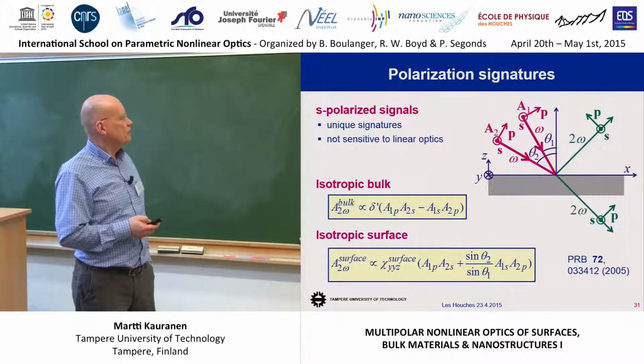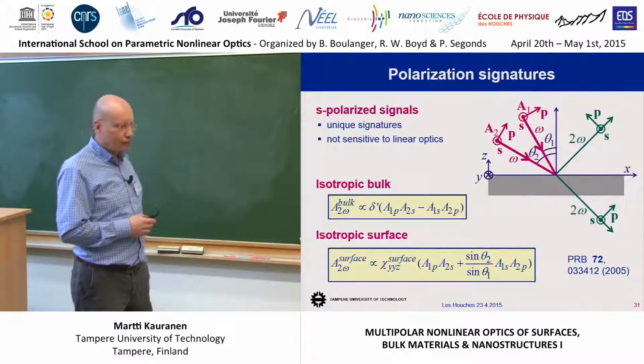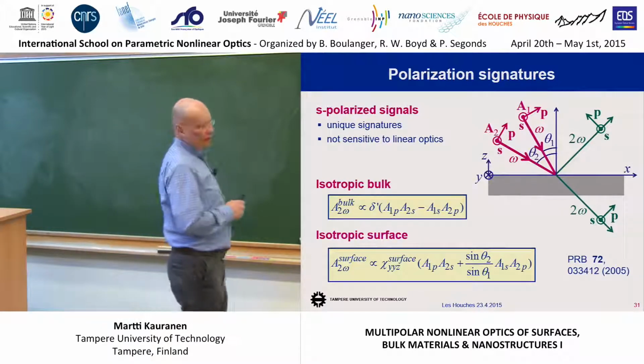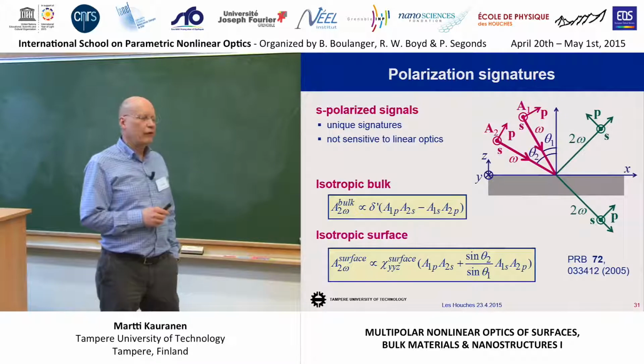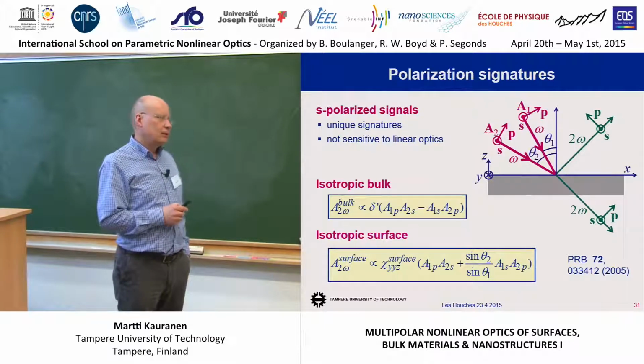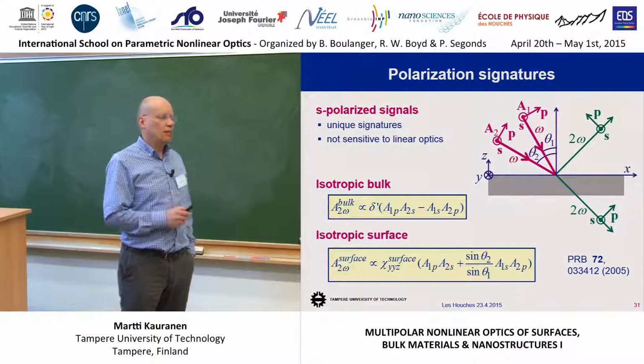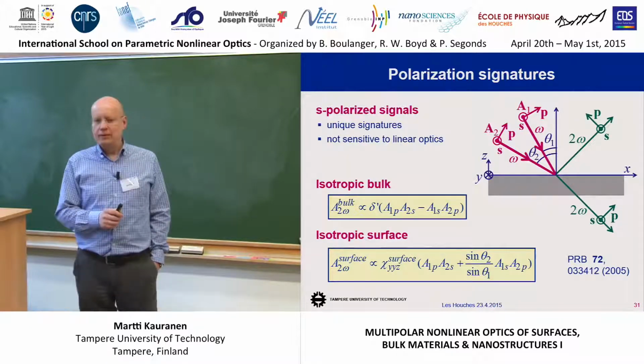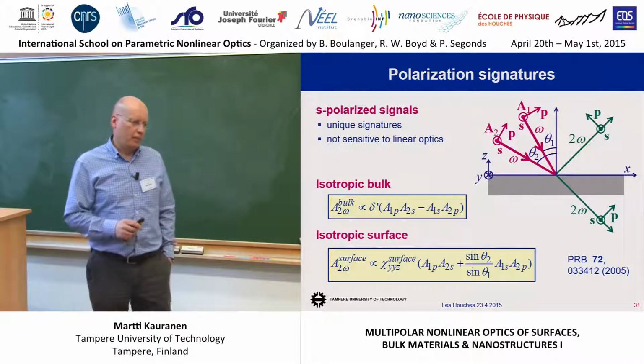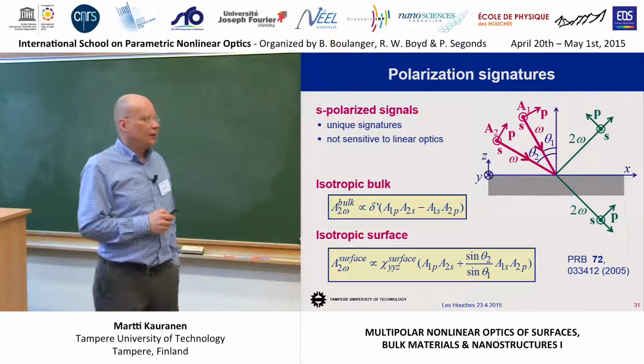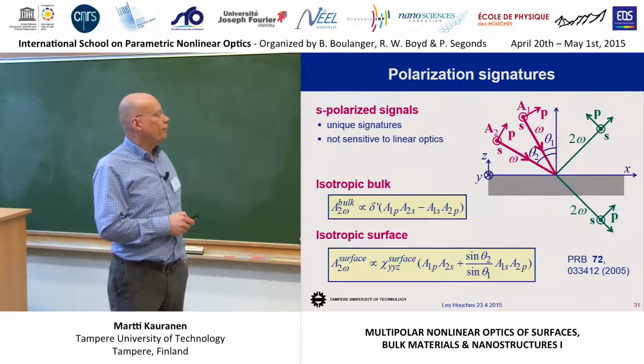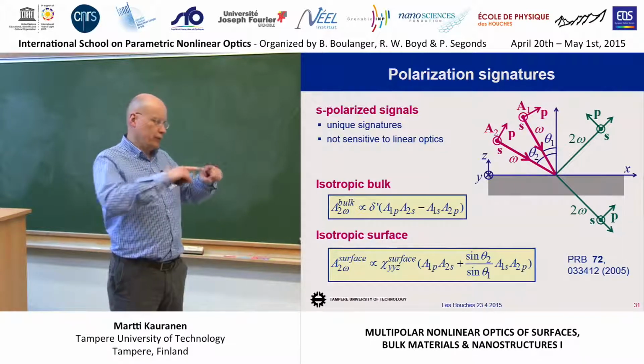We got into this accidentally. We were working on thin films in order to characterize their response within the electric-dipole approximation and as precisely as possible. And we realized that in order to have more parameters that we can control in the experiment, it's better to use 2 input beams.